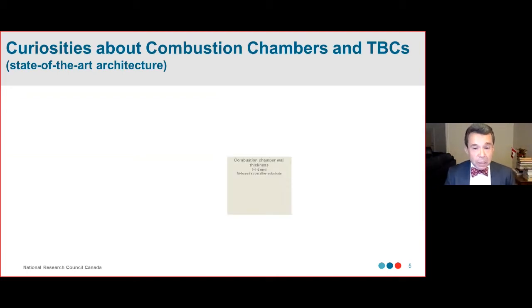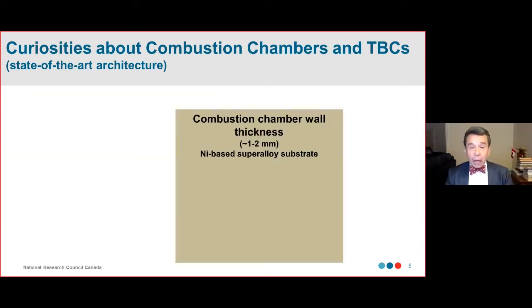Okay, so, well, some curiosities about the combustion chambers and TBCs, the state-of-the-art architecture of TBCs for combustion chambers. Basically, to have an idea, the combustion chamber wall thickness is only 1 to 2 millimeters thick. So when you are flying, this thickness here is about 1.5 millimeters. When you're flying, the combustion chamber metal, the nickel-based alloy, has a thickness of only about 1 to 2 millimeters, and you are burning the fuel at high power. Basically, the temperature is higher than the melting point of the material. So it's amazing, isn't it?